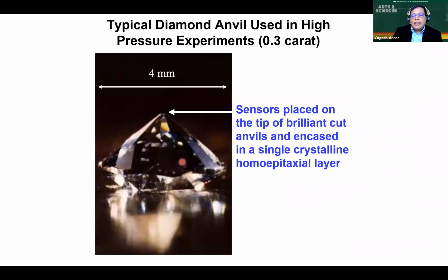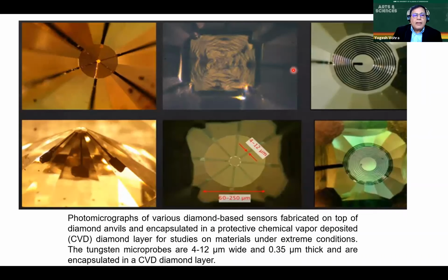So how do we actually accomplish this in practice? So imagine that you have a diamond crystal. This is about 1/3 of a carat, about 4 millimeter across. You fabricate a sensor on the tip of this diamond anvil with the microlithography, which I described in the previous viewgraph. And then after you have fabricated this sensor, you can actually put it in the microwave plasma chemical vapor deposition system and encapsulate these circuits.